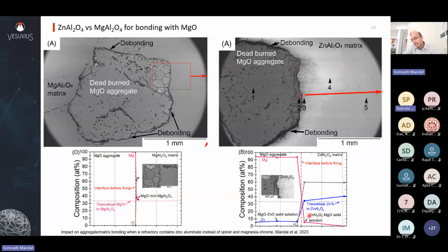So basically (Zn,Mg)Al2O4. So it's not fresh in situ magnesium aluminate as in the reaction of magnesia and alumina. There is no free alumina in here. So because there is no free alumina in this system, there is no free in situ spinel formation.